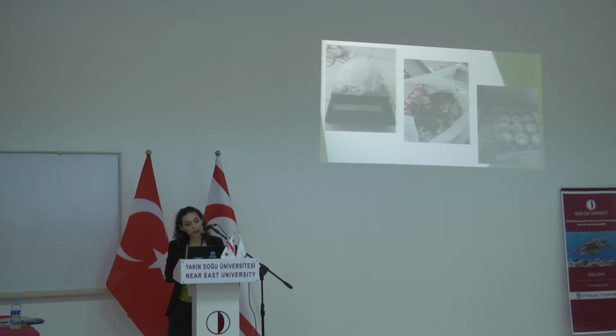So here you can see in the photograph, the left one are the strips of the plastic. It was almost 4 to 1 centimeter cuts, and it was mixed with soil. And for finding the water content, they were put in the oven at 100 degrees, and we found that this temperature doesn't burn the plastic.